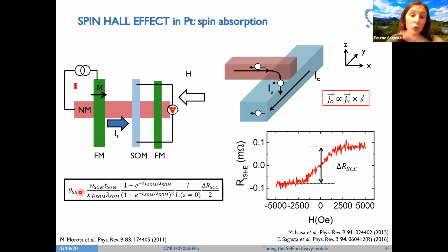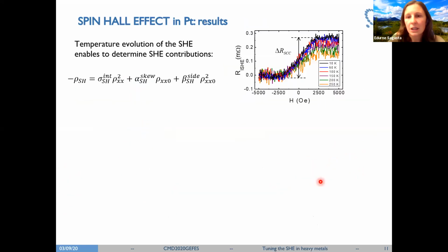Of course, as I showed you before, if we know the spin Hall angle value, we also know the spin Hall resistivity value and the spin Hall conductivity value, considering the equations. So now we perform this experiment at different temperatures. So here we can see the result.